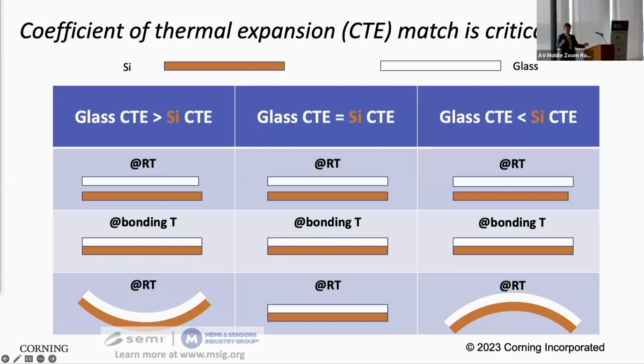CTE, the thermal expansion coefficient, is critical when you bond at high temperature and then you cool it back down to room temperature for device usage. This illustrates what happens if the thermal expansion is higher than silicon, the same, or lower than silicon. If the glass CTE is too high, then after bonding and cooling, you will have a curvature due to the glass essentially shrinking more than the silicon. And the opposite is true when the glass CTE is too low. And in the middle, when you match the CTE precisely, the bonded wafer stays flat back to room temperature or any other temperature in between. So we want to choose the glass with the CTE precisely matched to silicon.